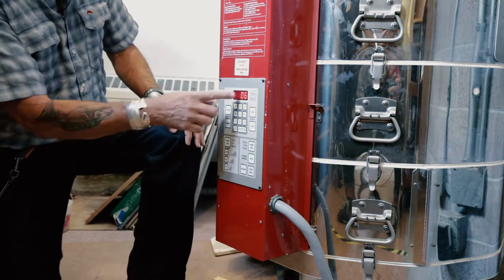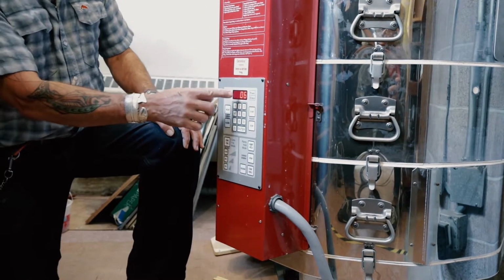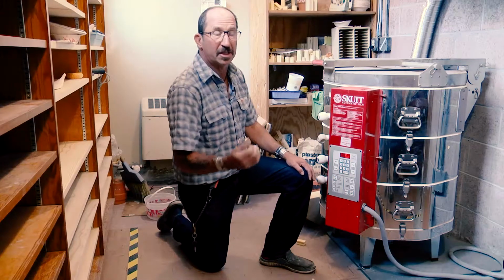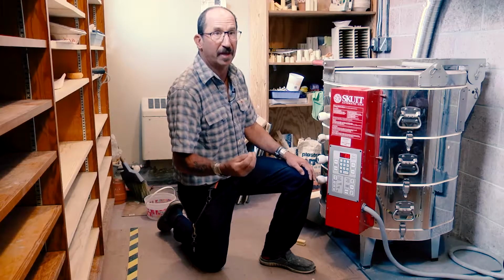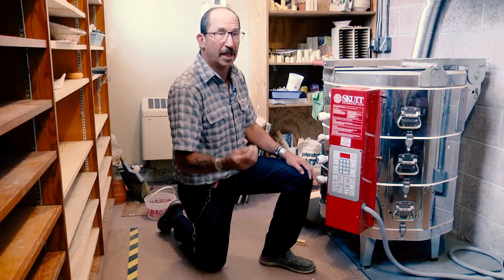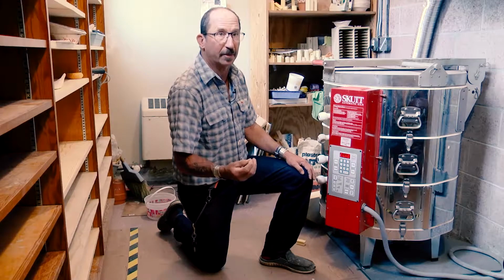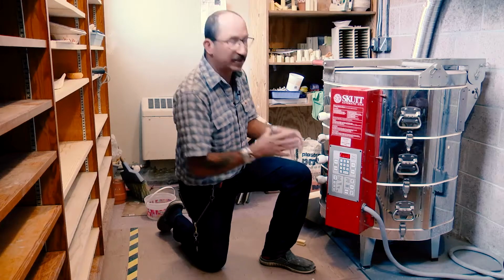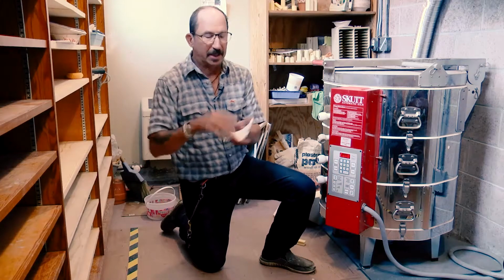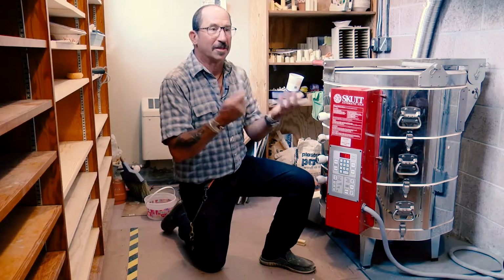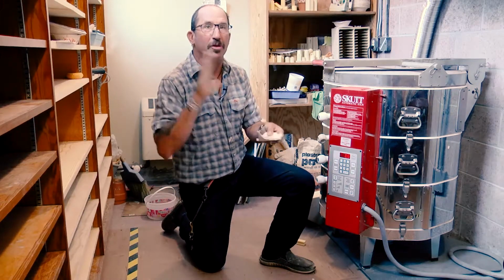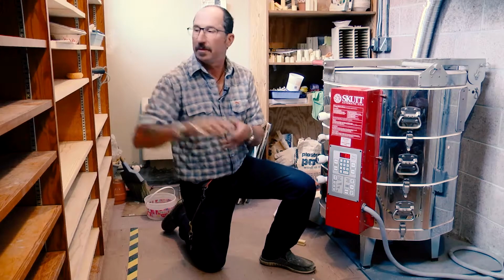So we hit enter. What cone do you want to go to? This says 06. 06 is the cone we want to bisque fire to. That's 1,815 degrees Fahrenheit, by the way. So that's the bisque temperature that'll allow things to get to this hardness. It has now been fired, but it's still porous, so it'll absorb a glaze.